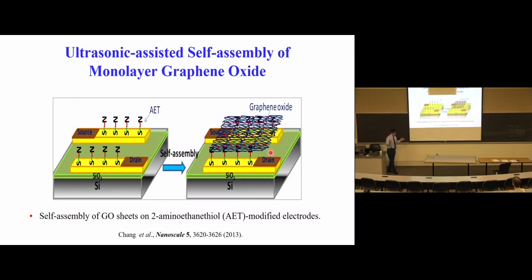So that's one example. With the molecular engineering of black phosphorus, we can enhance the sensitivity of the device. Now, the next example is using reduced graphene oxide, which is chemically modified graphene, as a sensing channel, for the reasons of this stability issue with the BP, right? BP is not as stable, but even with the passivation layer, you will see degradation of the sensing performance over the course of a few weeks.